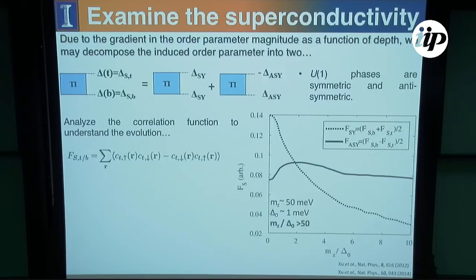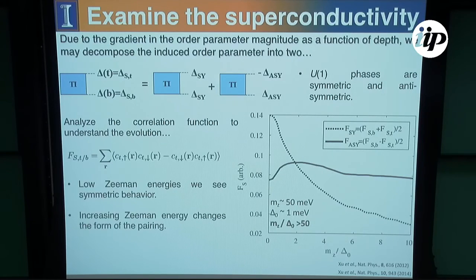So naturally, what we do then is we look at the top and bottom surface correlation functions for the superconductivity, and we've plugged in all of the parameters that we have for the experimental system that we took from both of these papers. You can see that as we increase the Zeeman splitting for these two different sectors, the antisymmetric sector, so this is pairing between electrons within the same sector, is going to be dominant over the symmetric pairing. Okay, this changes the form of the pairing.